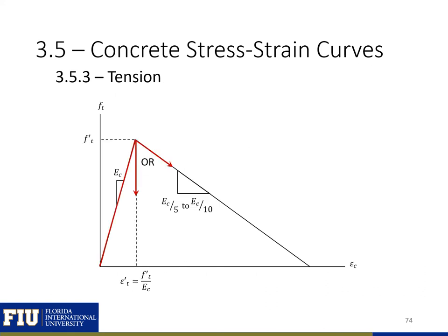The tension behavior of concrete up until the tensile strength can either be represented as a straight line with slope Ec or a parabola. In this class, we will assume that strain will vary linearly with tensile stress up until the tensile capacity of the concrete. The slope of this ascending branch will be Ec, the secant modulus found before. You can assume that the descending branch either drops in stress immediately after reaching the ultimate tensile strength with no additional increase in strain, or you can assume the descending branch has a slope of Ec over 5 to Ec over 10.